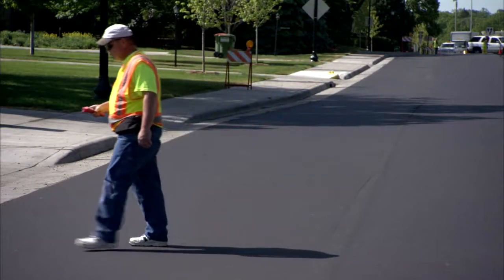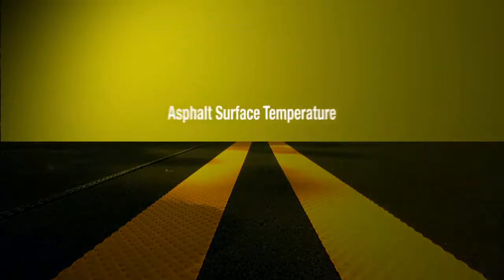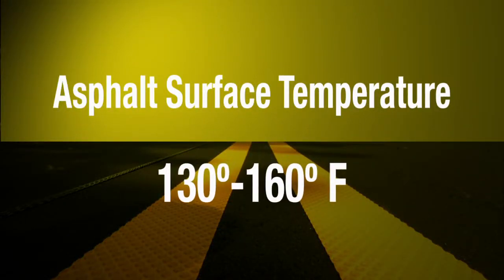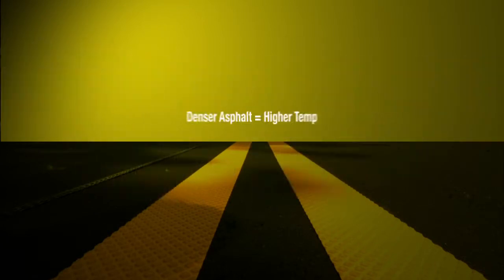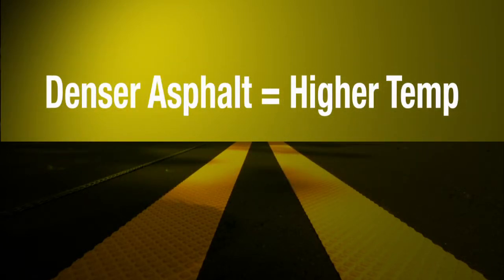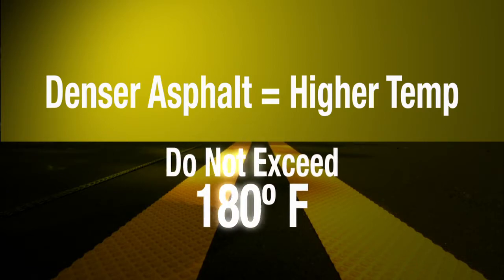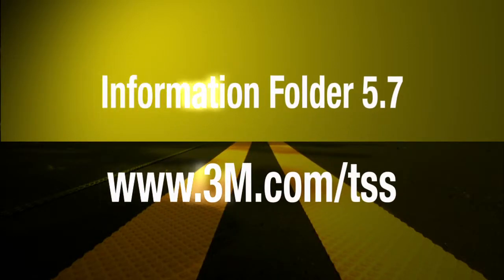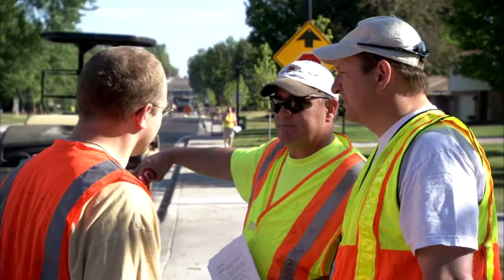the desired range. Generally, the asphalt surface temperature should be between 130 and 160 degrees Fahrenheit, but this range can vary depending on the asphalt conditions. Denser asphalt mix may require a higher temperature to achieve proper tape embedment, but never exceed 180 degrees Fahrenheit. See Information Folder 5.7 for detailed information about asphalt mixes and inlay temperatures. Experience will help you determine the right temperature range for your application.